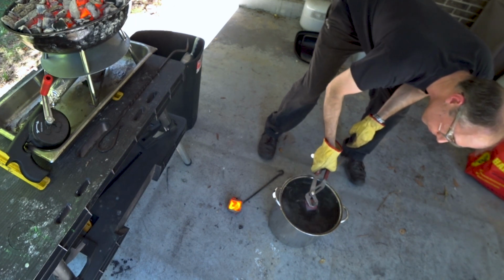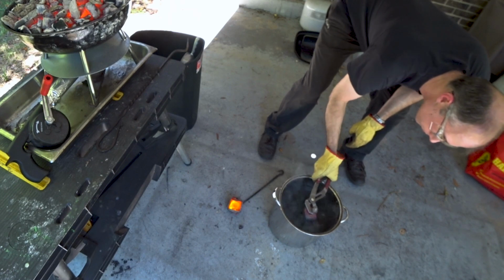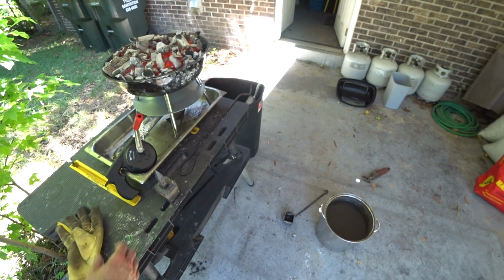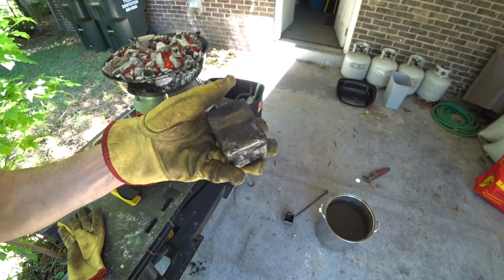I thought it was kind of interesting that you could see the last little bit of charcoal burning away in the clay cap as I'm quenching. It's still a little too warm to hold without gloves, but as long as it's below about 300 degrees Fahrenheit, the transformation should be complete.